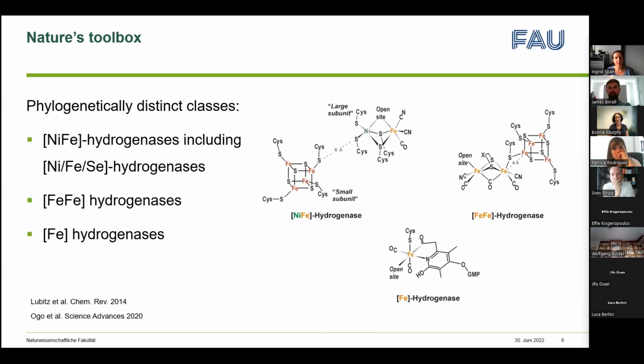So the toolbox that nature has is 3 distinct classes of hydrogenases, and the classes are divided according to the metal cofactor. So we have nickel-iron hydrogenases. We just heard about nickel-iron hydrogenases. The active site consists of a 4-iron 4-sulfur cluster and a nickel-iron cluster. This bimetallic cluster is similar to the iron-iron hydrogenase, which has an iron-iron cluster. And there is a 3rd class of hydrogenases, the so-called iron-only hydrogenase, with only 1 iron in the active site.